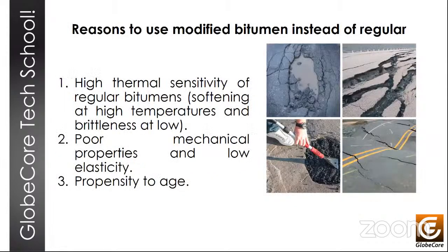For some time, advances in science and technology kept up with the requirements of the road industry. However, traffic intensity constantly increased, the traffic loads on road surfaces increased, and that caused premature deterioration and destruction of roads. Despite the fact that the technology of oil distillation was constantly improving, the quality of bitumen as a distillation product only got worse because of a deeper refining of oil in order to increase the output of fuels and other light fractions.